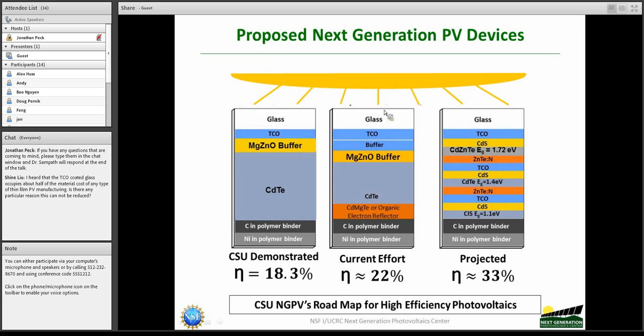And the current effort is in this structure that is here, where we have the glass and TCO, and there is something to be gained in going to a more transparent glass and a more transparent conducting oxide rather than the TEC 10 glass that was used here. That effort is currently underway, and maybe use another buffer layer and magnesium zinc oxide. Now, all this is to improve the current to the device. Then we have the cadmium telluride absorber, and a big amount of research right now is the magnesium cadmium telluride electron reflector, as we call it. And we are also exploring some organic semiconductors for doing this function. And then again, the back electrode contact is this carbon and nickel spray.